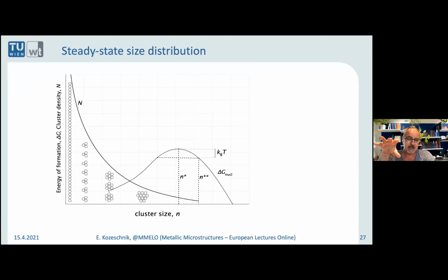And what you usually observe is that if you have a system which is not supersaturated, so let's say undersaturated, then you have a stable distribution of clusters of various size. Most of the clusters will be monomers, and the larger the cluster is, the fewer of these clusters exist. Following nucleation theory, the nucleation rate can be defined as the number of clusters of exactly critical size passing to critical size plus one. Keep in mind that nucleation is more or less the number of clusters that come over the critical size, the flux of clusters in cluster space.